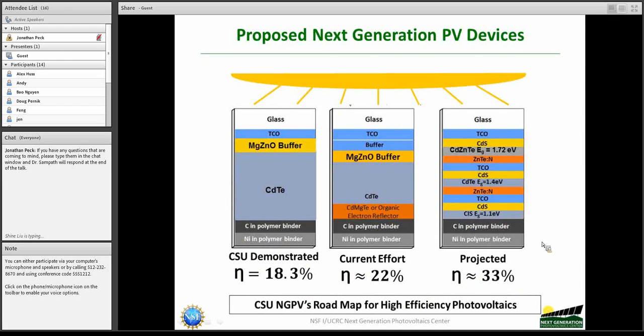So here are the proposed devices that we are investigating. Where we are currently, the technology is right here, where we take this commercially available glass with transparent conducting oxide and put this magnesium zinc oxide buffer that we worked quite a bit to develop. The cadmium telluride is the absorber, and these are back electrodes, which in the lab we sometimes make with just a carbon binder and a nickel binder, but in the industry it's mostly done by sputtering, and we are ourselves moving towards that soon.